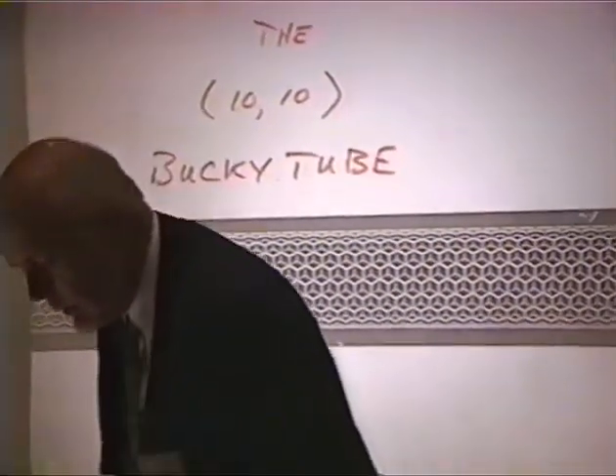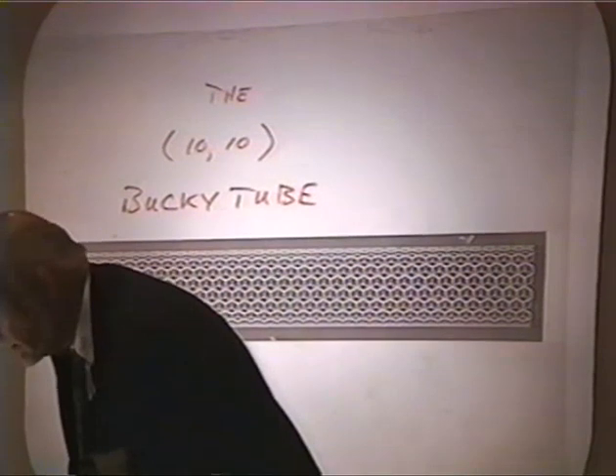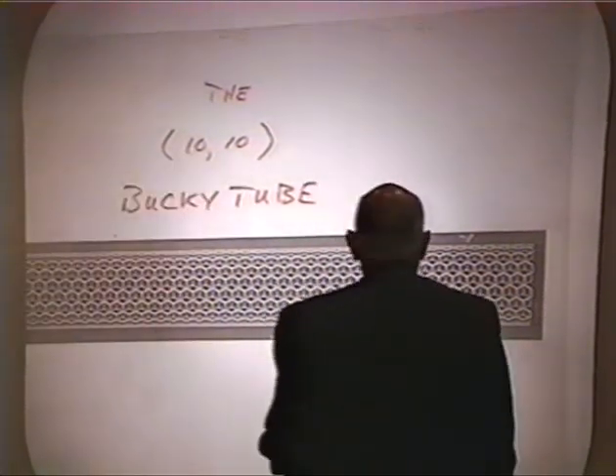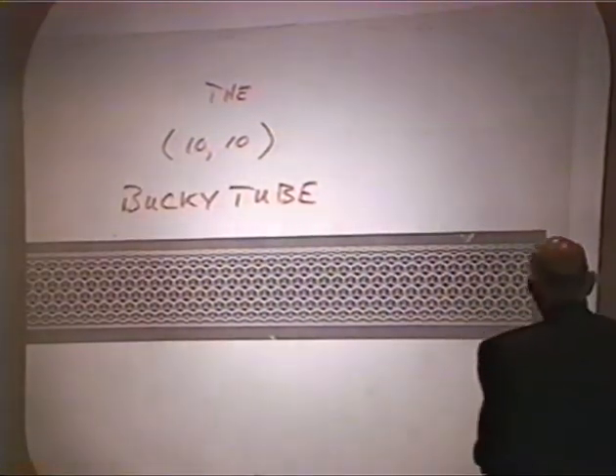There are two bands that cross the Fermi energy at 2/3 of the way across the Brillouin zone, and is forced to do that by symmetry. So this, as we'll see in a bit, as you've probably heard, turns out in fact to be a quantum wire.